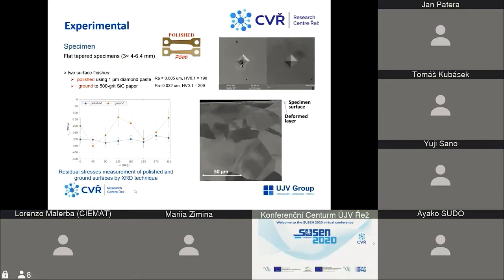So we have manufactured so-called flat tapered specimens. Here you can see the shape of the specimens. This shape is used to allow us to calculate the threshold stress, which is the minimum stress enabling the environmental assisted corrosion initiation. So owing to this taper shape of the gauge, we can determine the threshold stress of the test specimens from the location of the last crack along the gauge length.